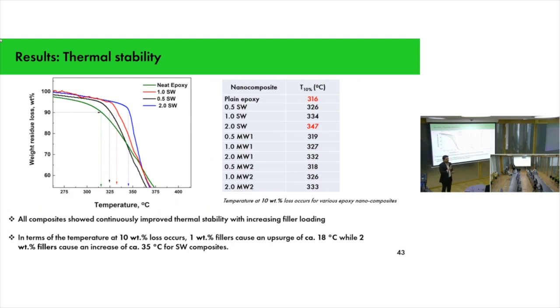So when we talk about thermal stability, at 10 weight percent thermal weight loss, compared to plain epoxy, our 2 weight percent single wall carbon nanotubes had the highest temperature compared to the other two multi-wall carbon nanotubes. So all composites showed continuously improved thermal stability with increasing filler content. When you look at the temperature at 10 weight percent loss, 1 weight percent goes up 18 degrees Celsius, whereas 2 weight percent increases the temperature by 35 degrees Celsius for single wall.